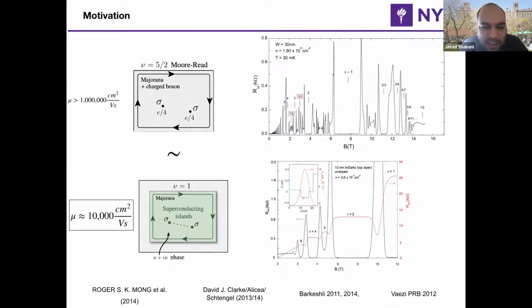But there is an equivalent picture, I think, which was proposed around 2012 to 2014, that if you bring a superconductor to interact with an integer quantum Hall effect, maybe a similar physics can be created, which was alluded to by Beenakker earlier on, that this is a Majorana fermion. And in some particular case, you make it more exotic with fractions, it could be parafermion. But for integer quantum Hall effect, the requirements are much lower. I don't need a 20 million mobility sample. I can live with 10,000, 20,000, 100,000 samples. So in terms of the material growth, it opens up a path to other materials, but now we have to ask the question, which materials can actually interface with superconductivity?